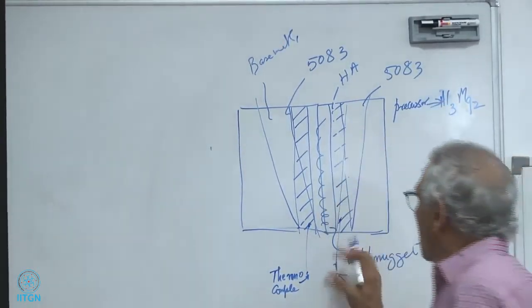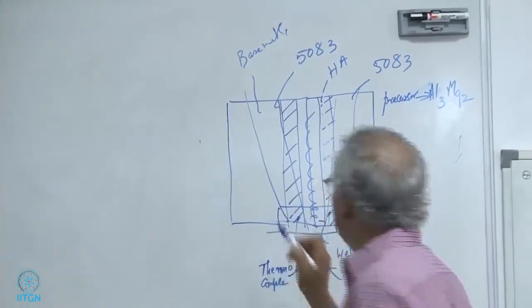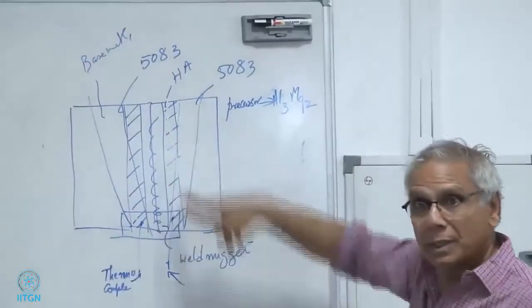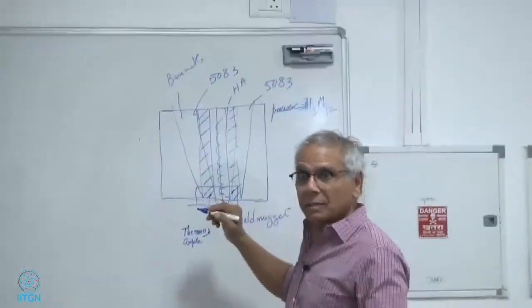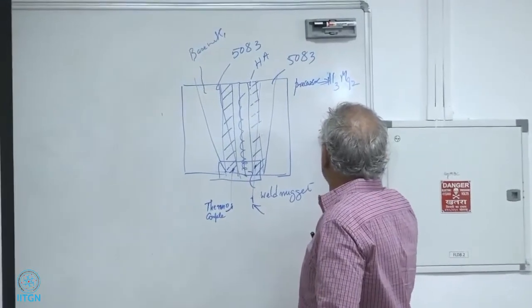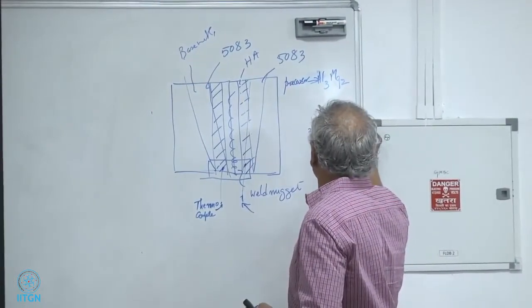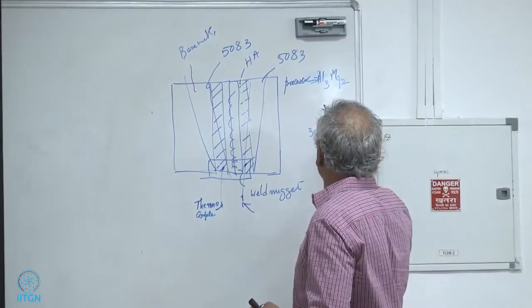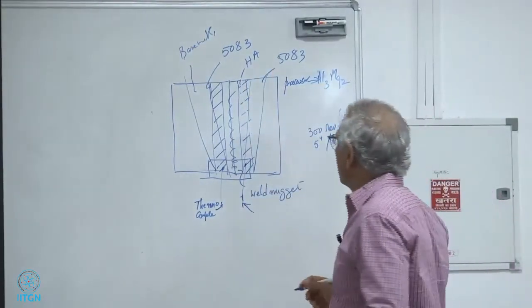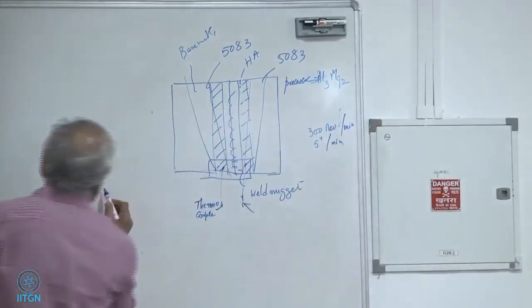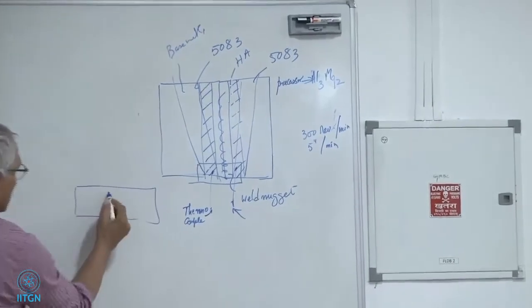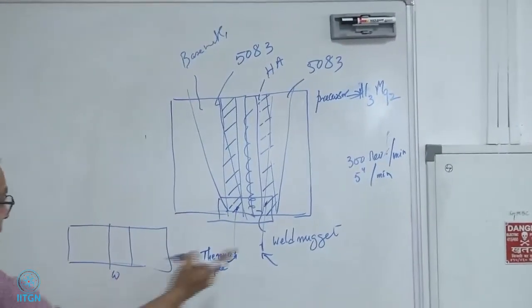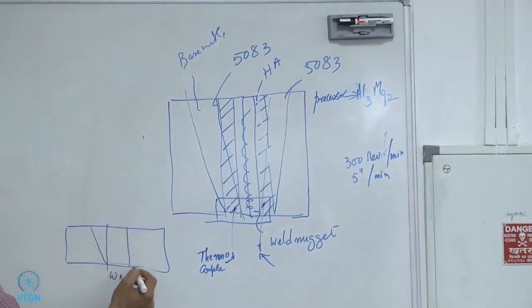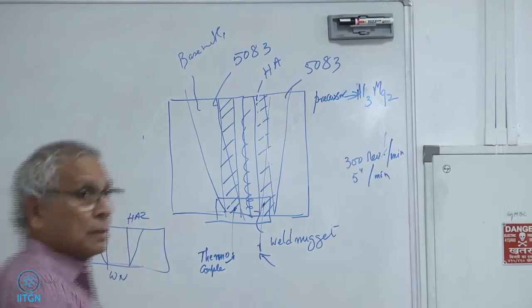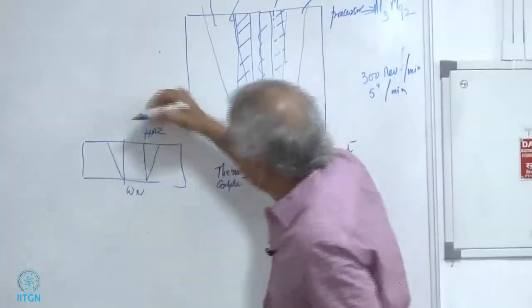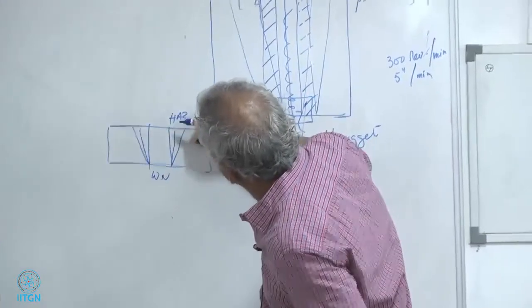Okay? So after you do all this, then you take a section, cut it perpendicular to the friction stir welding, FSW, axis, okay? Whatever it is, 300 revolutions per minute, or whatever is the best, 5 inches per minute translation speed, right? You make a section of that, then I'm going to have a section like this with the weld zone or the weld nugget, WN, my heat affected zone. And there is a thermomechanically affected zone also, right? There's also a TMAZ.